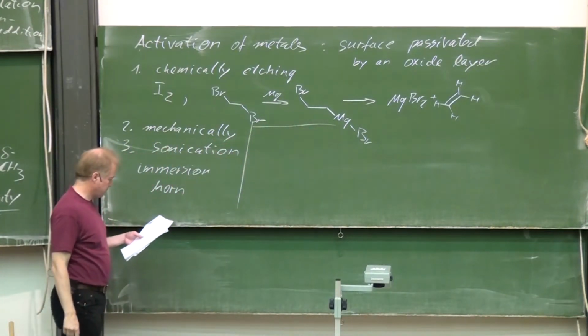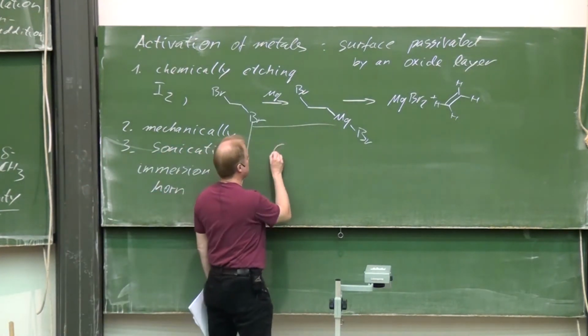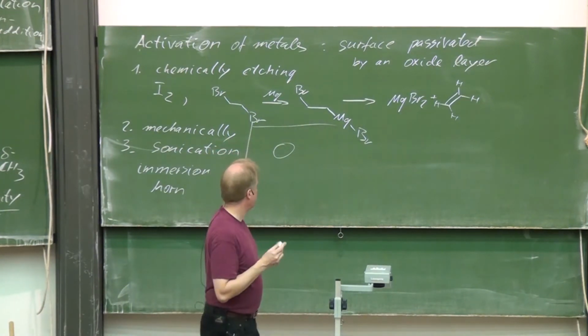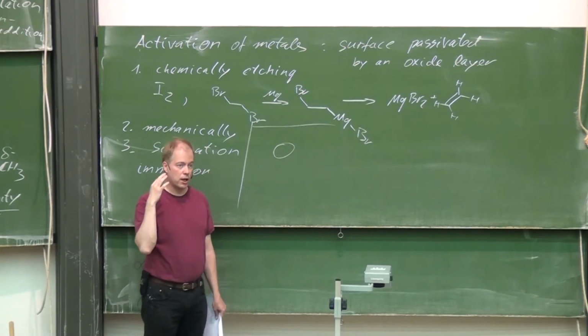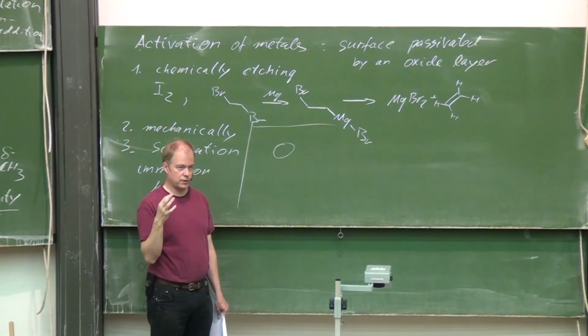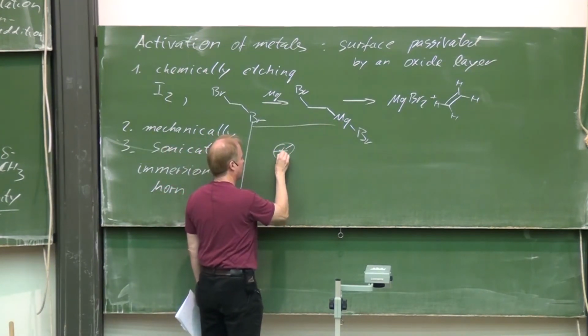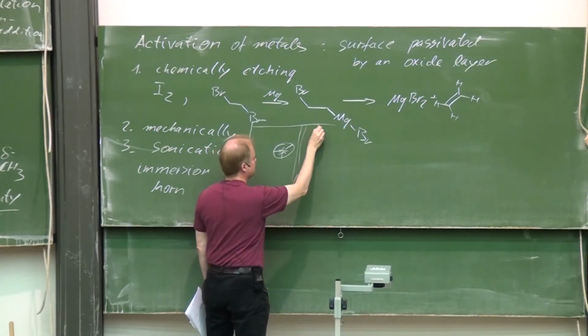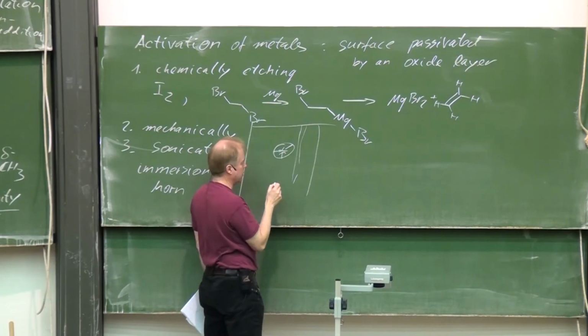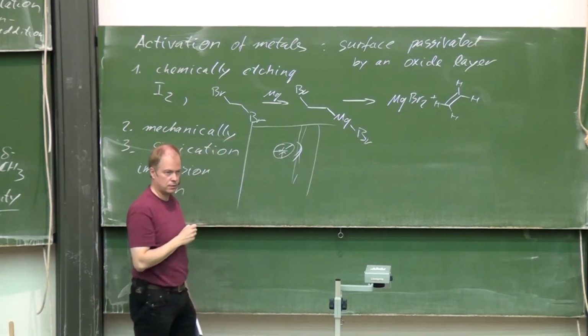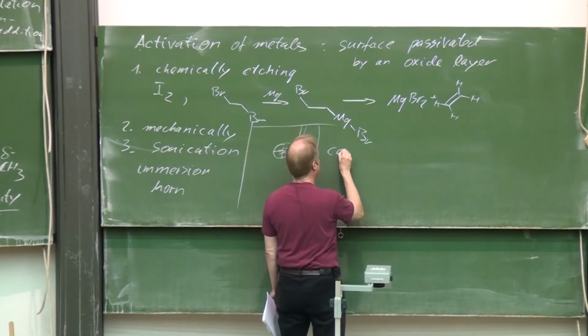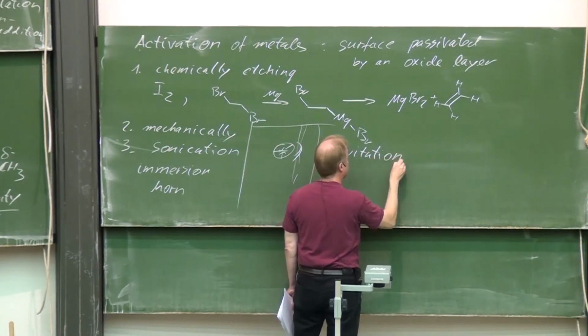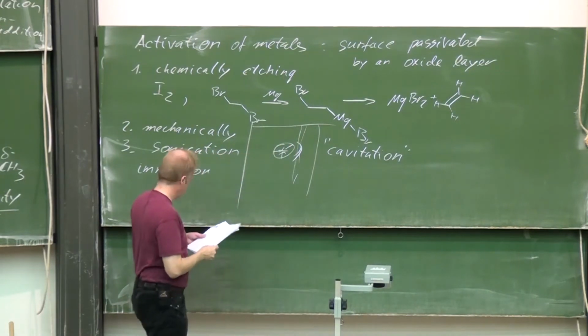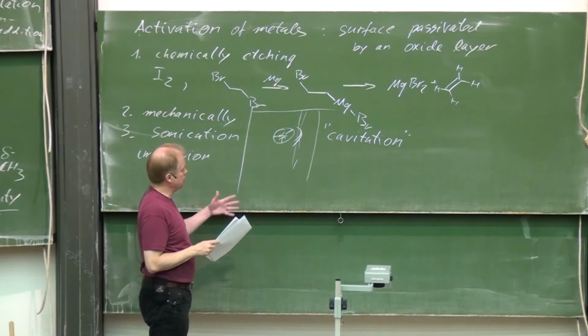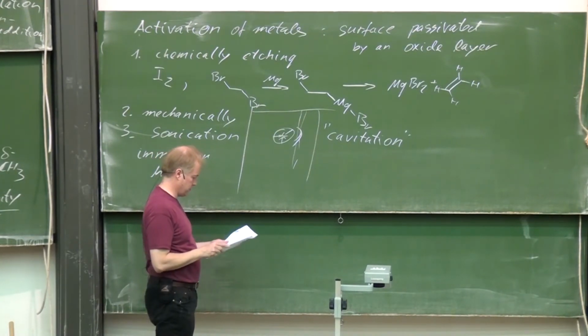So, how does this work? Well, generally it is assumed that ultrasound generates tiny little but very, very hot gas bubbles in the solution. They are very short-lived and they collapse. And if they collapse close to the surface with an oxide layer, then they bite holes into that layer. This process is called cavitation. So essentially it is, in that case, a cleaning of the metal surface.